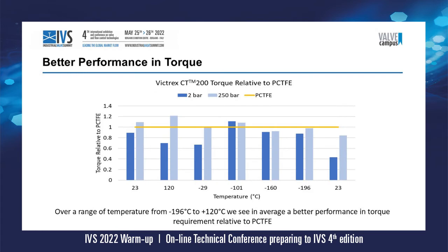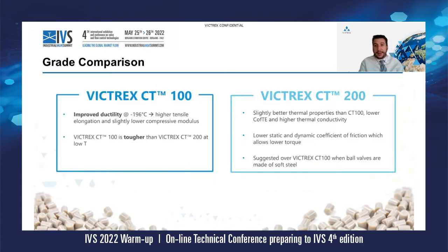The tests have also shown that the torque on average was lower. So either at 2 bars or 250 bars, so low pressure or high pressure, if we see the torque given by PCTFE as 1, all along the range of temperature we had lower values. So to summarize, CT100 has an outstanding ductility and sealing capabilities with a great strength. CT200 has better thermal properties and a lower coefficient of friction.